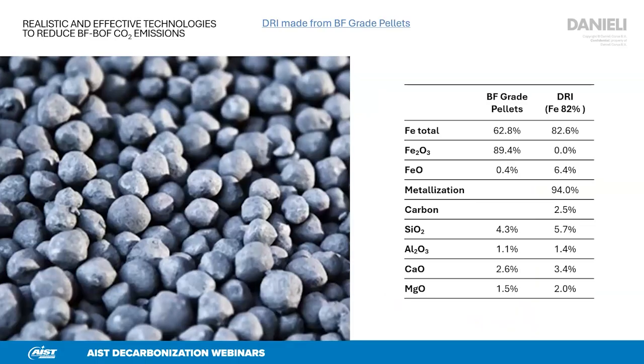Second to that, we know that high-grade ores are limited in availability. So ideally, our industry would be using lower-grade ores. Well, this is actually very attractive when charging this DRI in the blast furnace. So we have been looking into the usage of BF-grade pellets to produce a DRI with a lower iron content compared to an alternative scenario using DR-grade pellets, which would produce DRI with an iron content of more than 90%. So this DRI is, I would say, sort of low-grade DRI. It has a moderate metallization, but it has a relatively high amount of gangue components. And we can charge this in the blast furnace because the blast furnace is the ideal smelter.